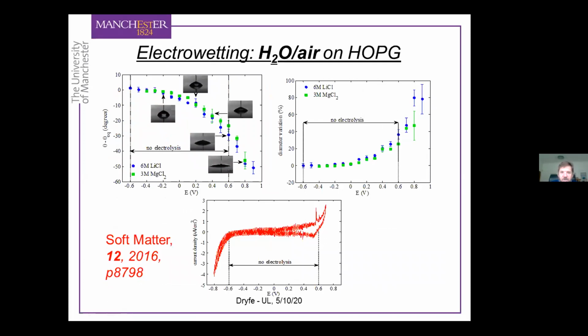And you can see that this effect is fairly reversible. You can see the change in the contact angle as we apply the potential. And basically, we can do this over many cycles. We can do this over hundreds of cycles. The contact angle is completely reversible over this potential range.